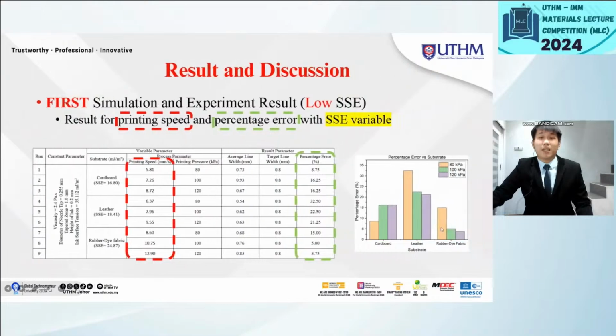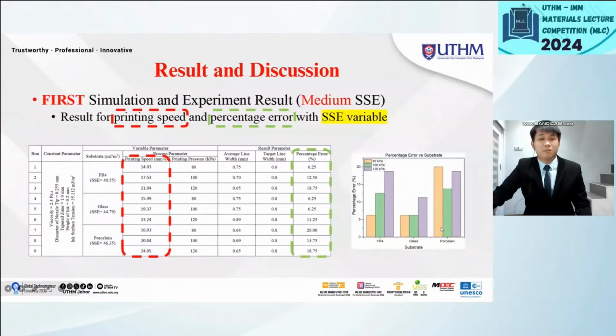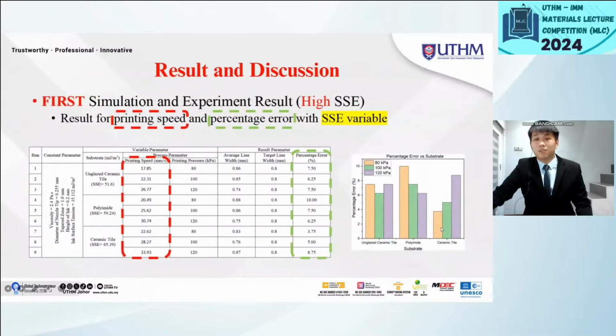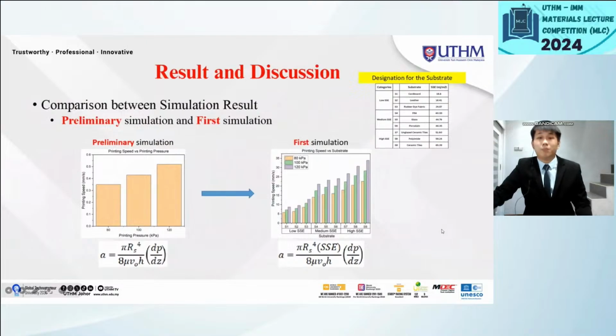Here are the tables showing the experimental results for low, medium, and high substrate surface energy conditions. This table presents the printing speeds and the corresponding percentage error for each SSE level. Next, I would like to discuss the comparisons between the preliminary simulations and the first simulations. The graph clearly shows that integrating the substrate surface energy variables into the existing models results in an increased printing speed. The highest printing speed for preliminary simulations is only 0.52 mm per second, whereas the highest speed for the first simulation reaches 33.93 mm per second.